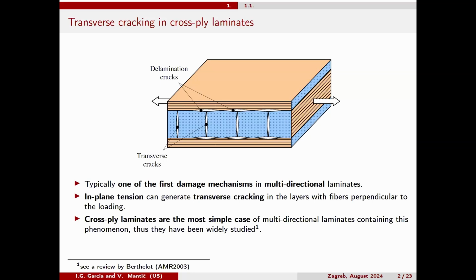And in this kind of laminate, we have a cracking problem that we call transverse cracking. They are cracks that are perpendicular to the load direction and are located inside the internal layer where the fibers are perpendicular to the loading. Actually, this cross-ply laminate is a very academic problem, but it is more or less representative of what happens in multidirectional laminates, which is what is actually used in the industry. So we are going to focus on this cross-ply laminate to study this phenomenon of transverse cracking, but the results can more or less be extrapolated to other, more complex multidirectional laminates.